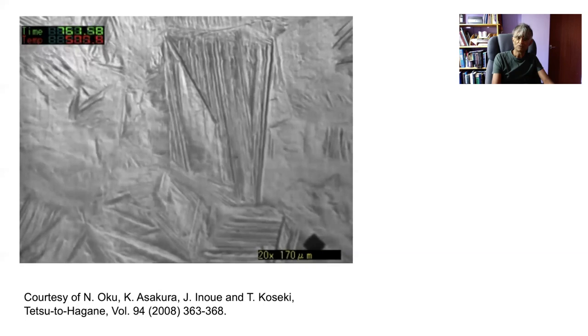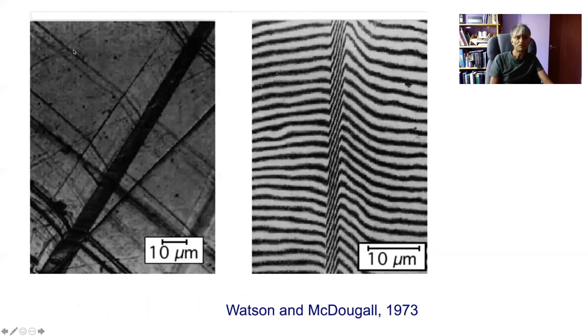And you can do other experiments to illustrate that. Here, for example, are scratches, which were straight when the material was austenitic, and they're deflected in the manner of a shear deformation by the formation of Widmanstätten ferrite plates. And these are Nomarski interference microscopy fringes, which are similar to the scratches, except they're not physical scratches, but caused by interference of light. And you can see that the fringes are displaced. Okay. Now, there is no question that there are displacements associated with this transformation.